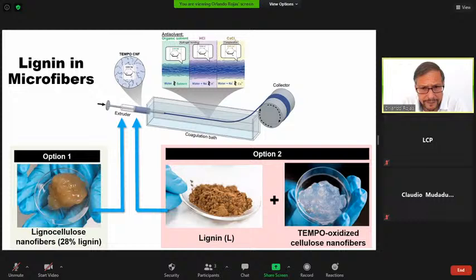Now, if we put back lignin that I mentioned before, we have been adding lignin by mixing lignin with TEMPO-oxidized nanocellulose. That would be option two on the right. But we could also have the residual lignin in the nanocellulose and use the natural lignin that exists in the nanomaterial. And in both cases, we can produce filaments. If we think on the right, what I want to say here is that filament spinning with pure lignin is extremely difficult. In the past, we have worked on lignin nanofibers using electrospinning and other techniques. But when it comes to wet spinning, as I showed, this is very difficult. So we need to add the component on the right, that is nanocellulose.